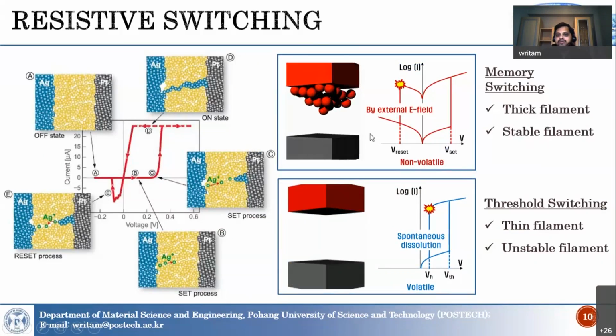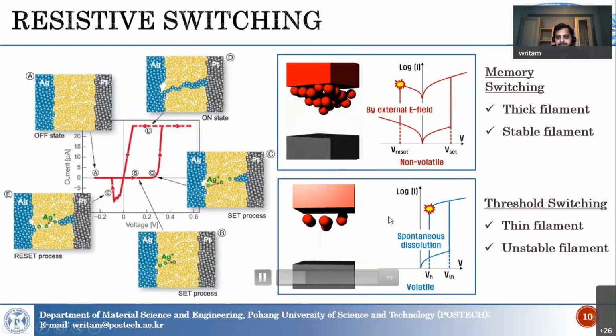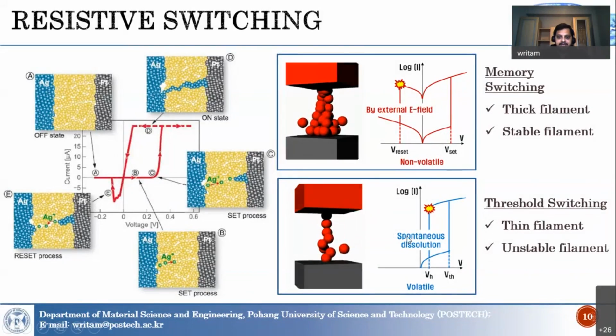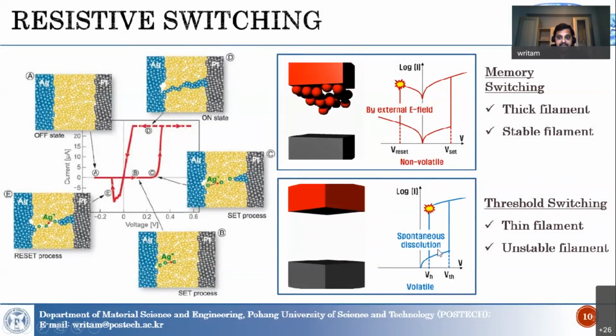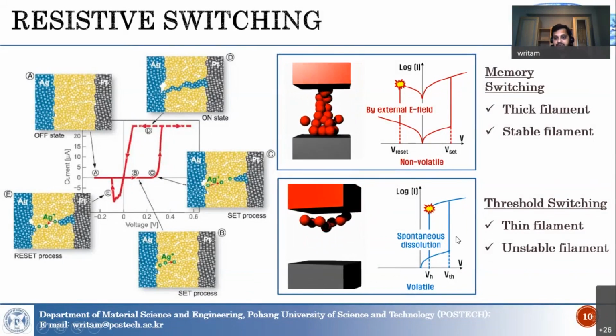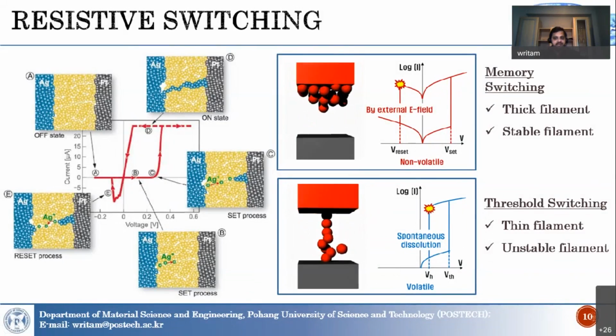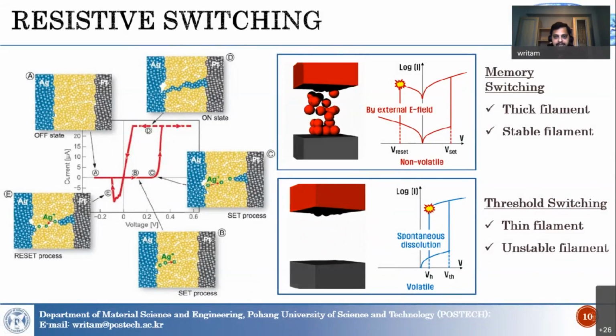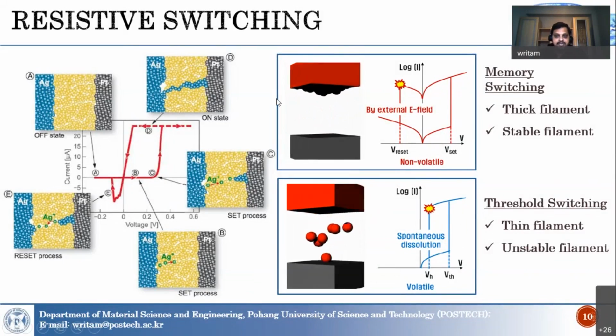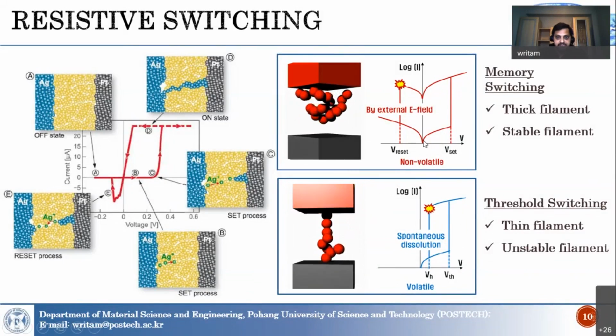Once we have a thick filament, you can understand a very stable channel forms. So this kind of device, the low resistance state is very stable, and they can be useful for memory applications. Now if instead you have a very thin filament, what will happen? It can break easily depending on the field, and those kinds of devices are suitable for selector devices, normally called threshold switching devices. So in this talk, I'm going to discuss both of them and how to achieve them in the same structure.